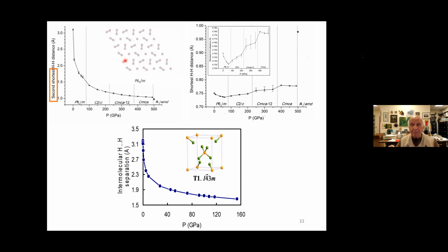That's the distance imposed by the van der Waals contact in solid hydrogen, for instance, at low temperatures. But look what happens to that. It follows a classical kind of equation of state curve, but the easiest thing to say about this: in the first 10 gigapascals of pressure, the first tenth of a million atmospheres that you apply, the distance between non-bonded hydrogens goes down by 1 angstrom.